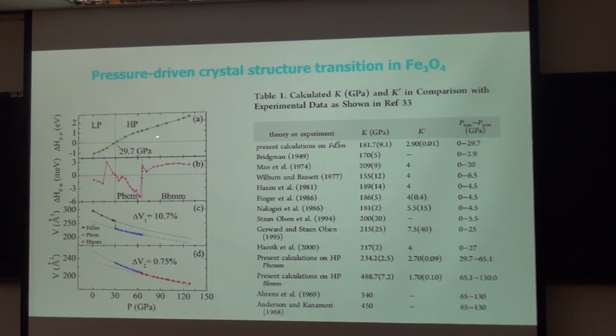But for the high pressure phase, we can find the energy difference between these two crystal symmetries is very small. But using accurate first principles methods, we can distinguish these two phases accurately. We can find the system will transition first to the Pbcm phase, and then to the Bbmm phase.